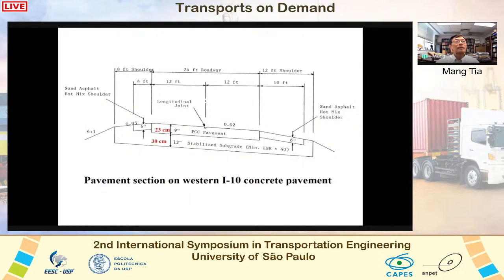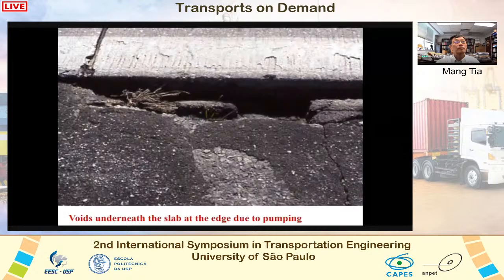And this figure shows the typical pavement design used on the older section of this concrete pavement. It had a 23 centimeter thick jointed concrete slab, and it had 30 centimeter of conventional stabilized subgrade. Unfortunately, no sub-drainage system was installed to allow water to be drained off this pavement. So as a result, pumping failure was observed on this concrete pavement.